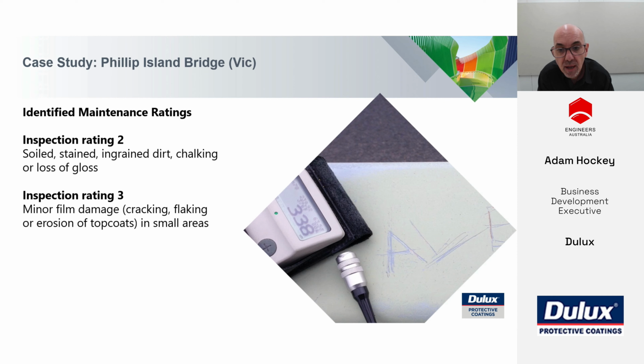So from an evaluation of looking at the coating system after this period, the recommendation would be to clean, sand and reapply just the top coat to reinstall the original coating system. One part that you can see in that photo where Alex has inscribed his name, I think he was inscribing Alex Loves Nicole, has caused what we call mechanical damage to the coating. So if we've got an area that's got mechanical damage, we would have to reinstall the coating thicknesses in those areas to make sure it's consistent with the rest of the coating.